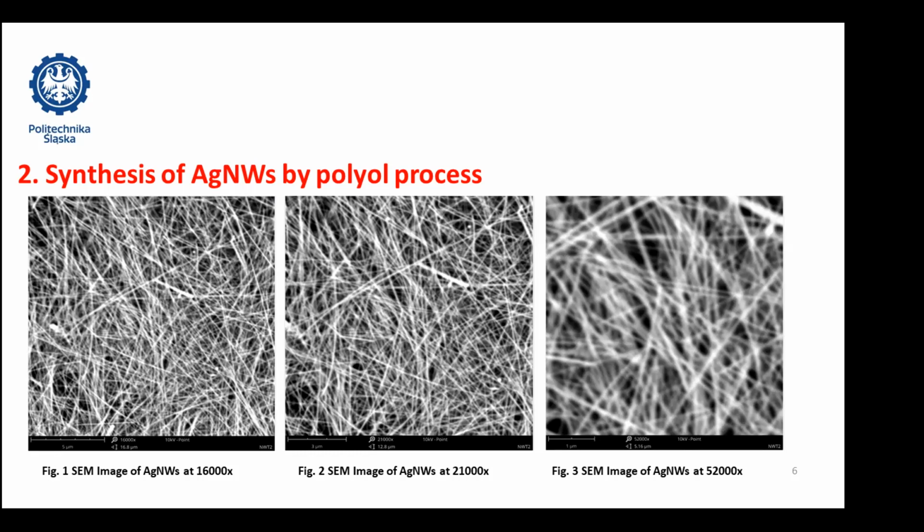So I will be quickly telling about my ingredients, which were PVP, ethylene glycol, AgNO3, copper(II) chloride. These were mixed together, and the solution was heated to 150 degrees Celsius for 70 minutes, and we got our silver nanowires. So I will briefly discuss the role of each ingredient.